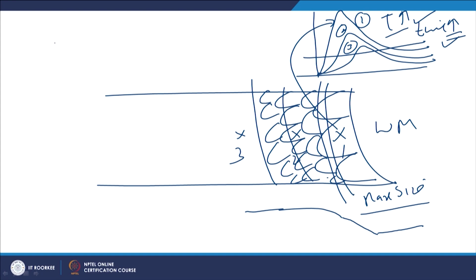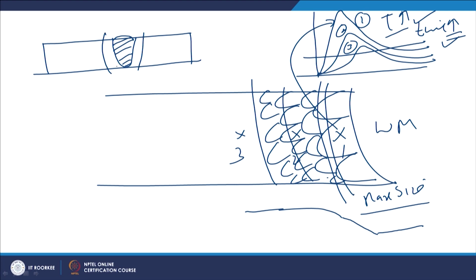So, if we plot the hardness variation for the weld joint of the metal strengthened by grain refinement, in that case the weld metal will have the strength corresponding to its dendritic size, but in case of the heat affected zone, the area next to the fusion boundary will be coarser, then somewhat finer slightly away from the fusion boundary.